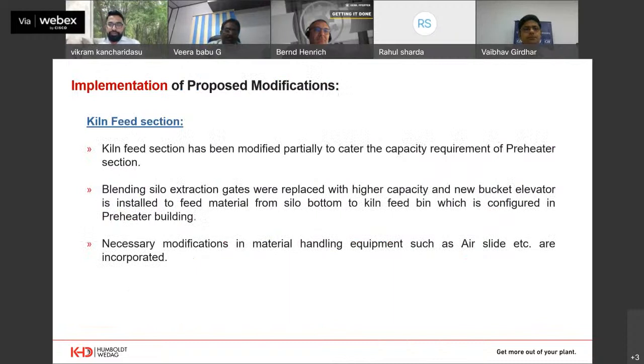Coming to the implementation of the proposed modifications, in the kiln feed section, we have modified the areas and components where the capacity was lower. We have identified what capacity we can guarantee from this kiln and what capacity we can achieve. Based on that, we have estimated the capacity balancing. Through that, certain equipment we have modified, like the extraction gates from the blending silo, the air slides, transportation air slides, and also the elevator feeding to the kiln feed bin. And also the kiln feed flow meter system.